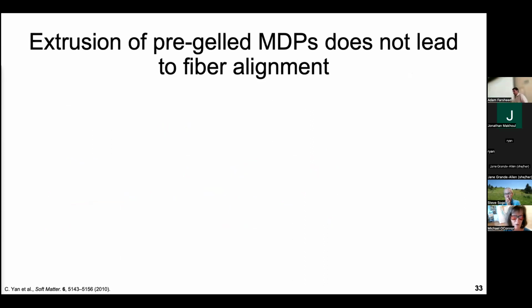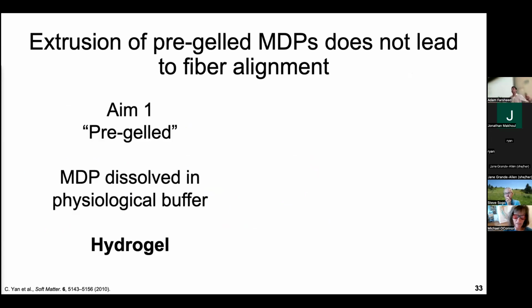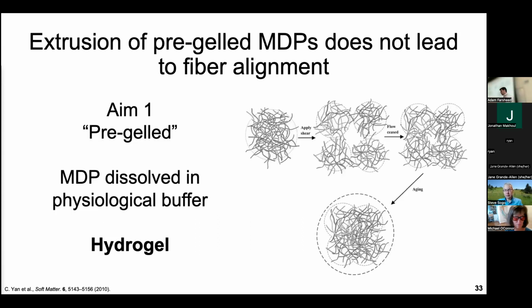And so this is going to get a little bit confusing here, but I hope to break it down for all of us. In AIM-1, in all of that work, we were using a gel, a hydrogel. And from now on, I'm going to call that pre-gelled. And again, what that was is an MDP dissolved in a physiological buffer that creates a hydrogel. And there is some mechanistic understanding from another self-assembling peptide system, where when you apply a shear force, you don't actually see fiber alignment. And there's a hypothesis that what happens is the macroscopic nanofibrous structure will break down into smaller domains that are small enough to flow. And unfortunately, if you shear them and stop shearing them, we will not achieve fiber alignment.